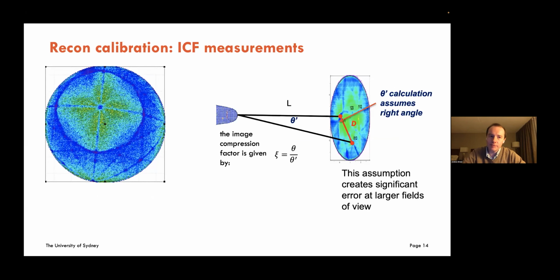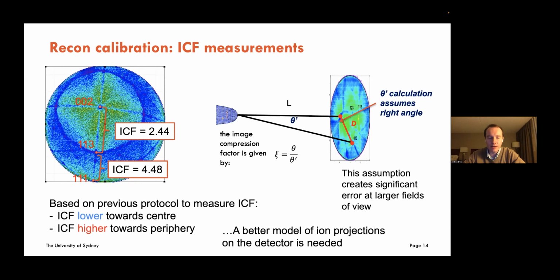But reconstruction calibration is a bit more challenging in the Invizo because we're going out to those larger fields of view. I think the ways in which we go about calculating image compression factor need to be reviewed. It might not work so well for the Invizo. If you go through and try to work out an image compression factor on this test aluminium data set here, it's quite small at the center, but quite large out towards the periphery. So a better model for ion projections on the detector for the Invizo is needed, and that's something we're working on and discussing with Cameca.